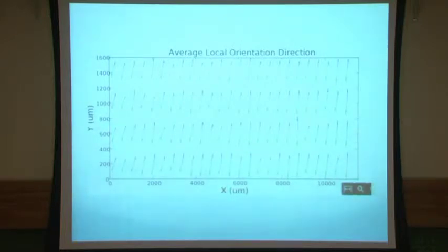Am I correct here? So this is a centimeter by millimeter sample, right? And we've done it on larger samples even. You can see that this average alignment of the defects propagates through an entire sample, right? And so this really is a dynamical nematic phase of liquid crystals that preferentially move in one direction, right?